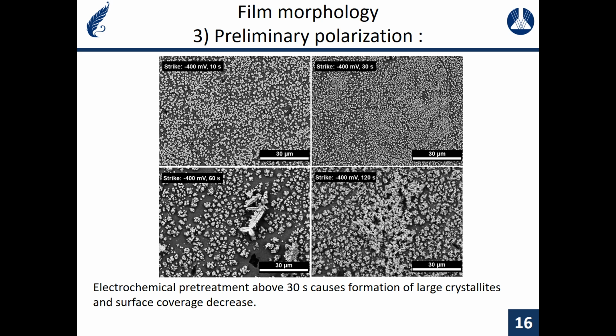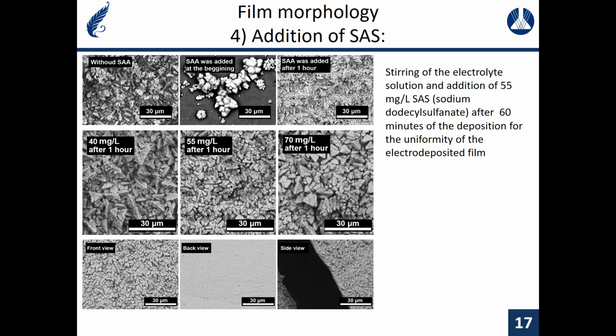We used pretreatment at -400 mV for 30 seconds to provide uniform coverage of the stainless steel electrode surface. Longer pretreatment leads to the formation of large crystals. To avoid non-uniform electrodeposition, also the solution has to be stirred and the surface active substance has to be added 60 minutes after the beginning of the electrodeposition. The time of the addition is important, as surface active substance prevents nucleation if added at too early stage.